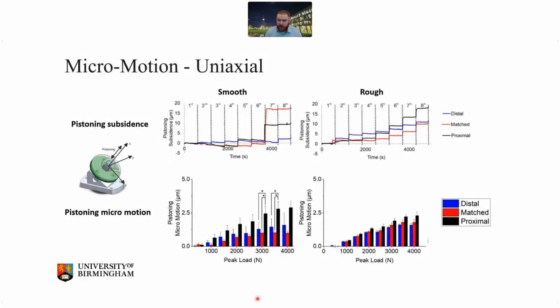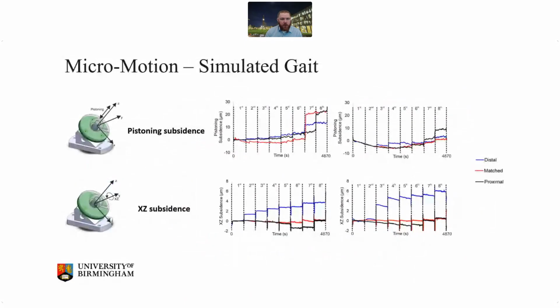And then the proximal taper, which again is kind of industry standard, that's driven by the design requirements for having a ceramic femoral head to make sure that you don't result in burst fracture, basically demonstrated a higher level of measured corrosion currents, high level of pistoning, sorry. That was also true,